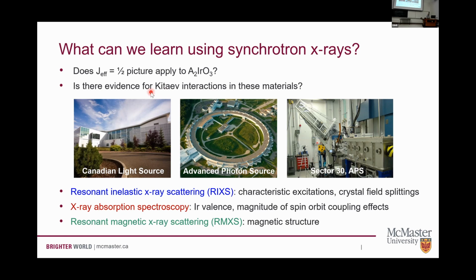And so we use 3 different synchrotron X-ray techniques. What we call resonant inelastic X-ray scattering, or RIXS, lets us look at the characteristic magnetic or orbital excitations to map out these crystal field splittings. X-ray absorption spectroscopy lets us study the valence of the iridium and look at the size of the spin-orbit coupling. And then resonant magnetic X-ray scattering lets us determine what the magnetic structure is.